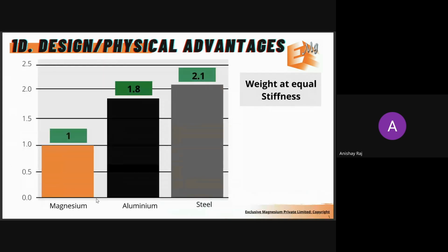The fourth is you can also reduce weight due to the ability to cast thin walls or to maintain stiffness at thin wall thickness. So this is weight at equal stiffness. Magnesium, as I mentioned, there are some features of your component that don't require load bearing strength. They just require stiffness. So in those sections, we encourage our customers to reduce the wall thickness, because magnesium can be cast in thin walls. If it was about 2 mm, you can reduce it to 1 mm. That is possible with magnesium, right?